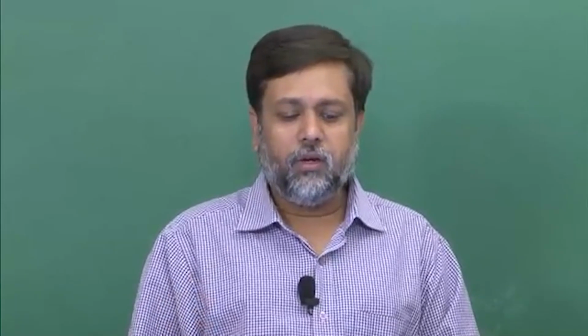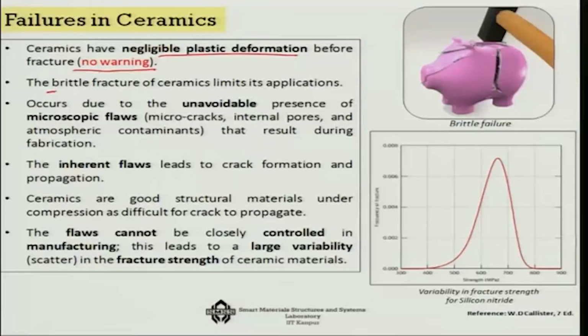You will see that bridges collapsing suddenly. Why? Because the steel that is supposed to be going there is not given, or it got corroded or something, and hence it is no longer a metallic driven failure where you will get a warning for quite some time, because it does not fall all of a sudden. On the other hand, if it is a ceramic governed failure, it will be a brittle fracture and it will happen all of a sudden. So, this is something that we see many a times.